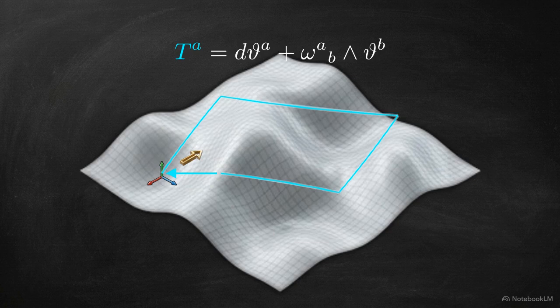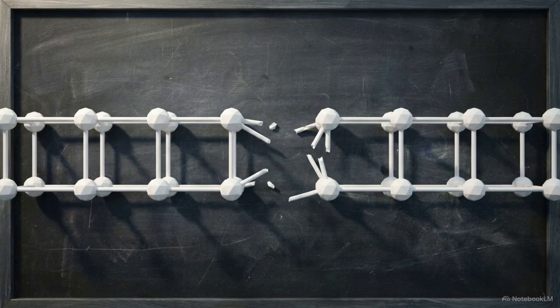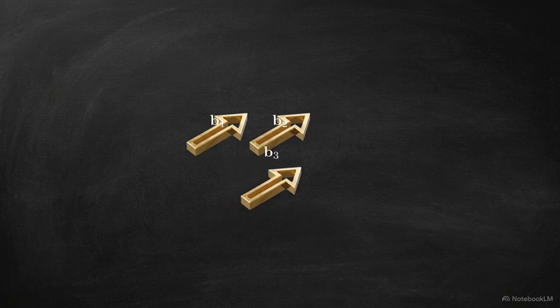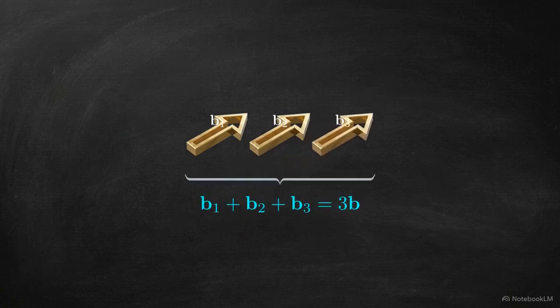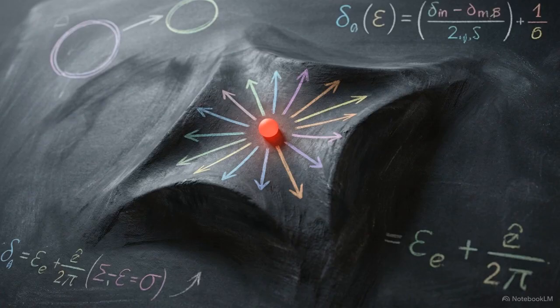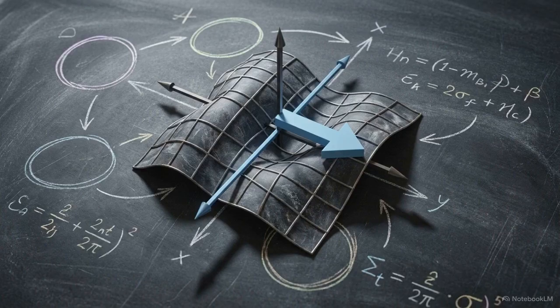The explicit geometric measure of this translational mismatch is called the material torsion two-form. This isolates specific defect types. In a crystalline material, pure dislocations generate torsion, while rotational defects, known as disclinations, generate material curvature. If a system contains only dislocations, you can simply add their translation vectors together. But when rotational disclinations are introduced, the translational holonomy becomes highly sensitive to your frame of reference and your starting base point. The full defect charge can no longer be treated as a free translation vector.